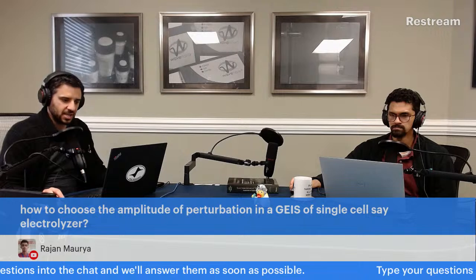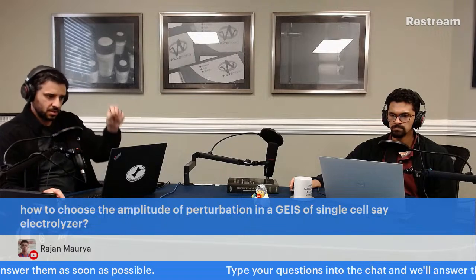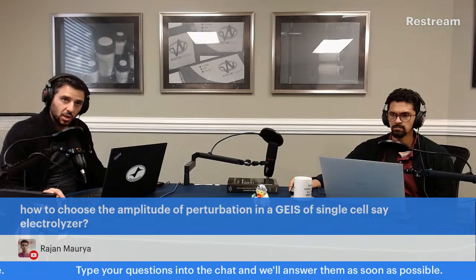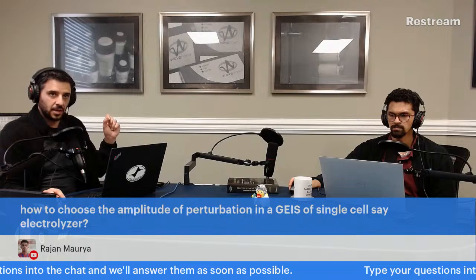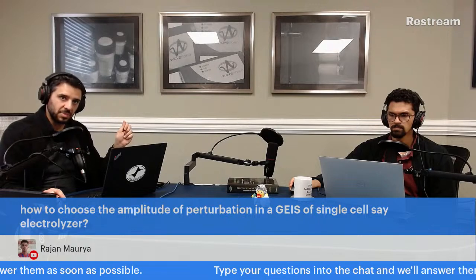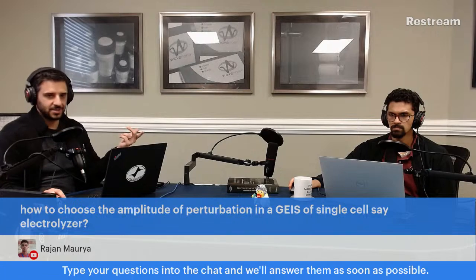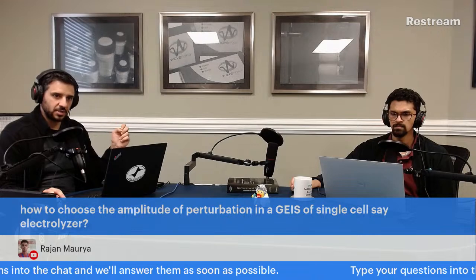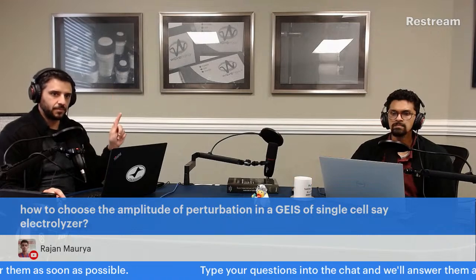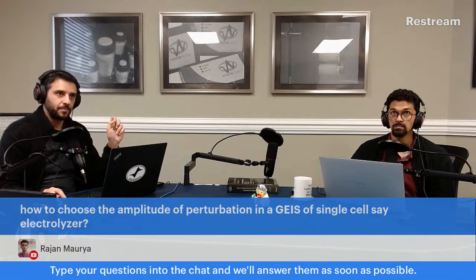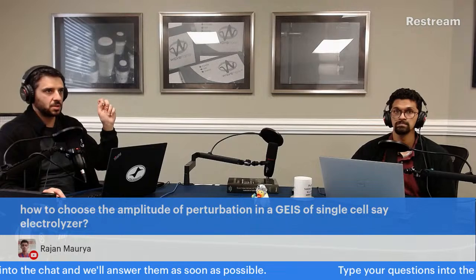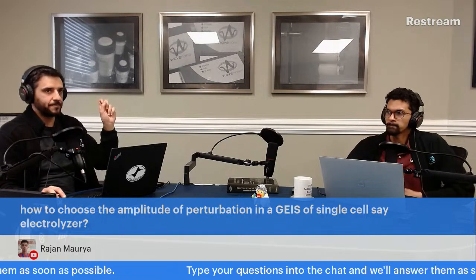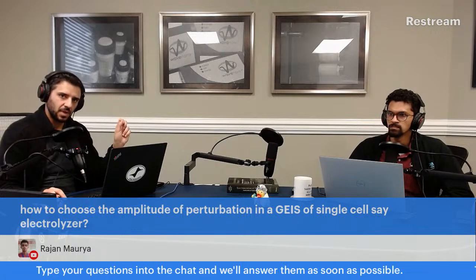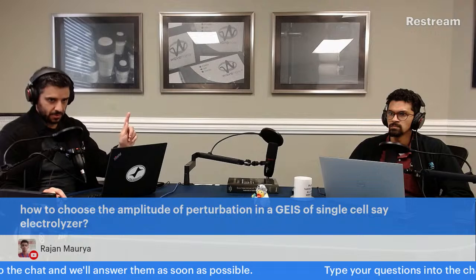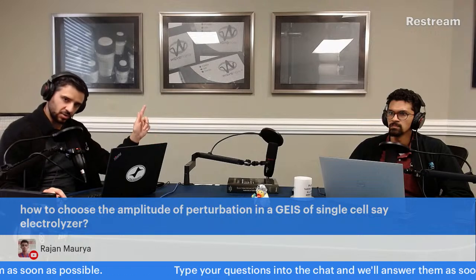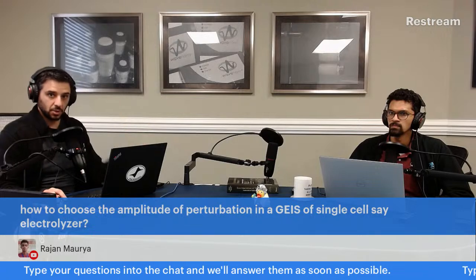And a lot of times what you'll see in your Bode plot or your Nyquist plot is a lot of noise. It gets worse as you get to low frequency, because at low frequency the impedance goes up, which means the response gets smaller, right? V is equal to IR or IZ, and you're applying a set current. If the impedance goes up, sorry, I said that backwards. It's going to be worse at high frequency than at low frequency. Because as you go to low frequency, the impedance goes up, which means the V response will also go up. And as the V response goes up, the resolution of your signal gets better.